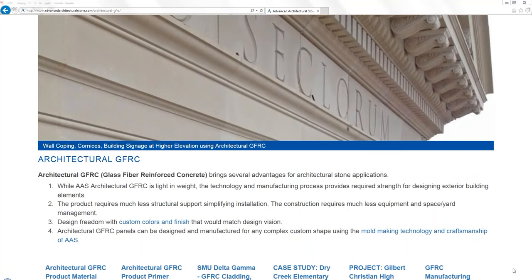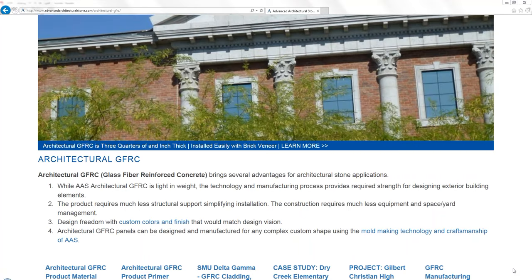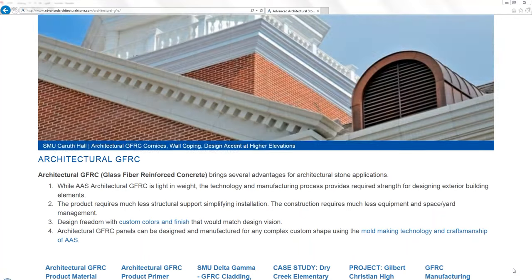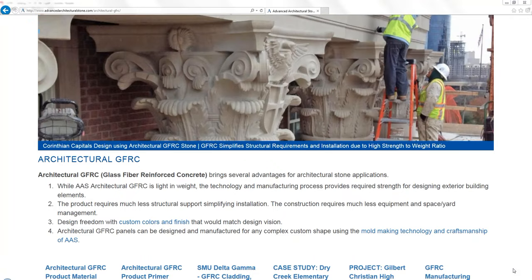In terms of creative architectural design, the possibilities for shape variation in the GFRC process provide a range of opportunities. The designer can choose deep reveals, complex shapes, sharp curves, short radius curves, wide sweeping arcs, 90-degree angles. A wide range of surface finishes are available. They're achieved by exposing the aggregate, acid washing, sandblasting, integral color, white cement, and textures can be used.